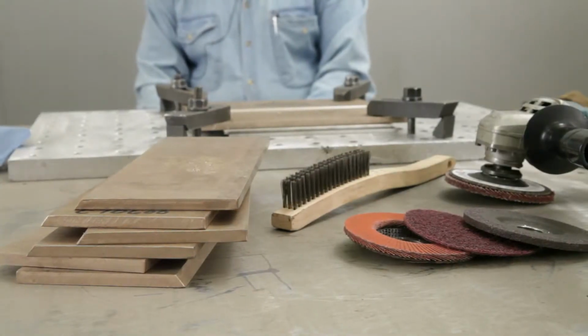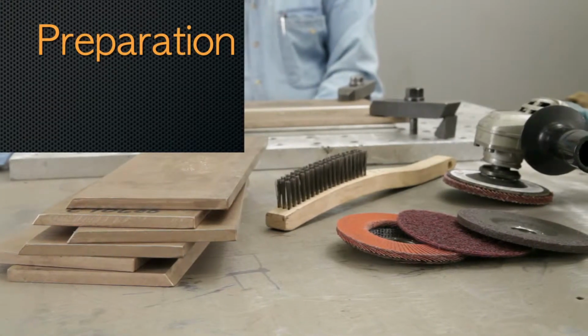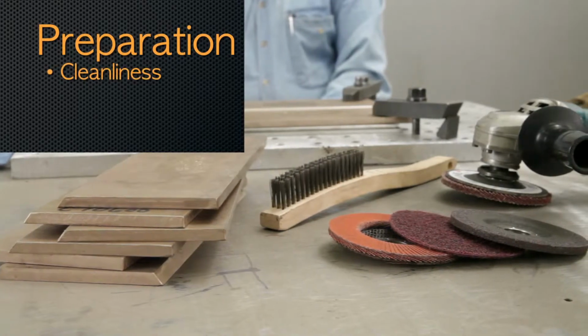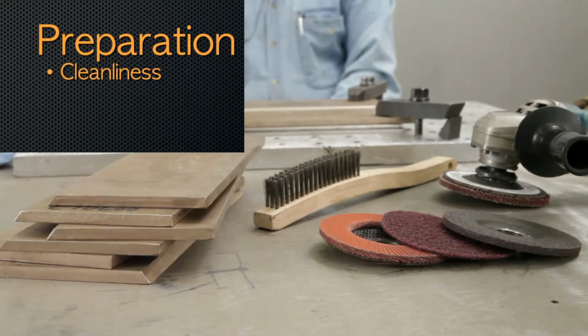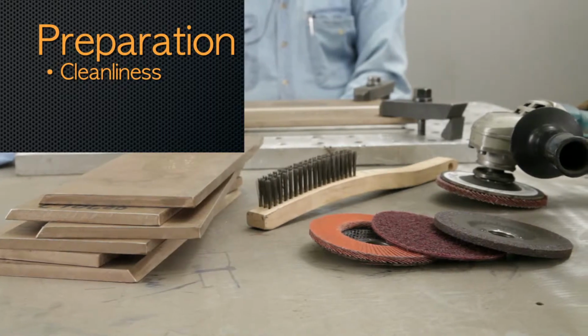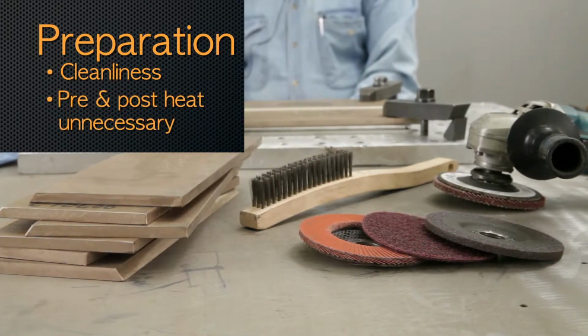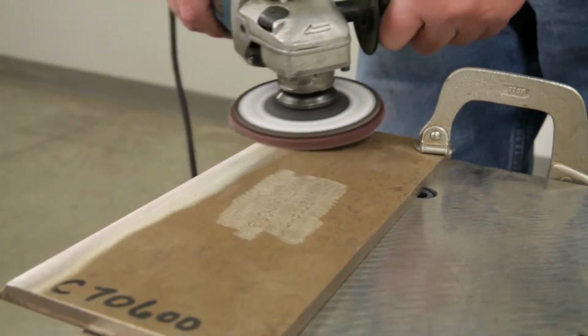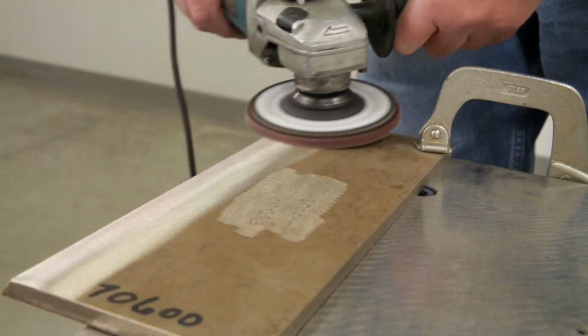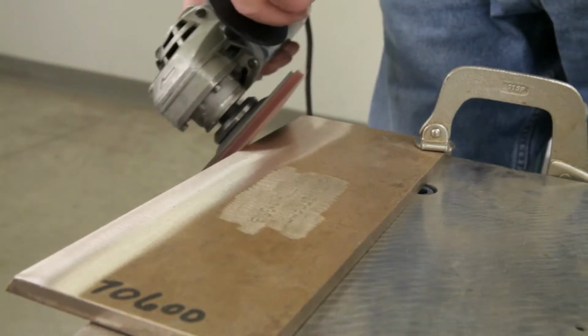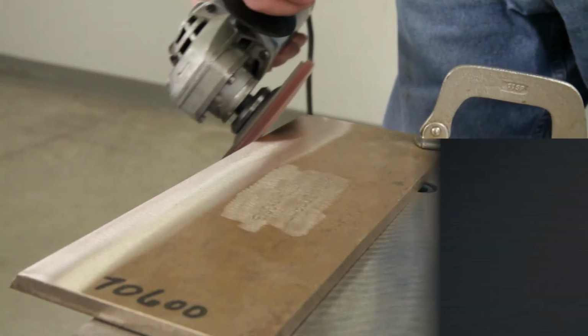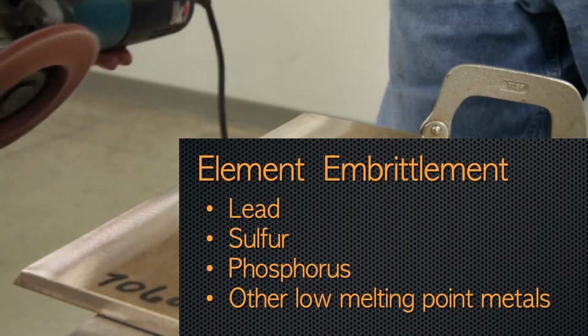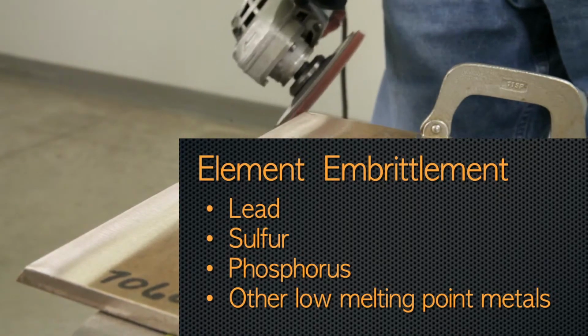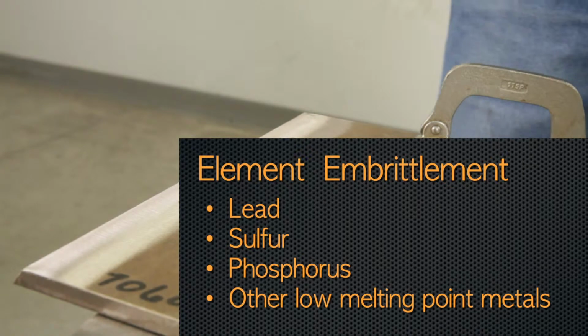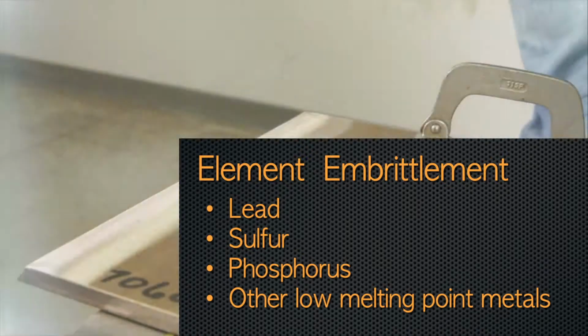To recap, in our first video, we covered preparation for welding. Maintain a high level of cleanliness and avoid contamination, which can cause weld cracking. Preheat and post-weld heat treatments are unnecessary. There are elements that even in small amounts are very detrimental to copper-nickel alloys, and if present on the surface before welding, they can cause embrittlement and cracking. The elements that are particularly harmful are lead, sulfur, phosphorus, and other low melting point metals.